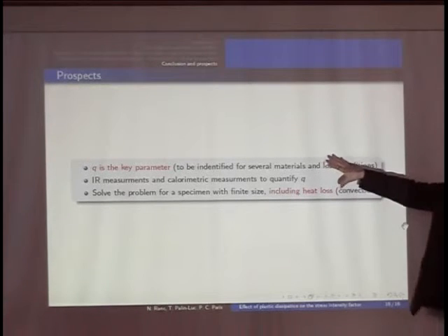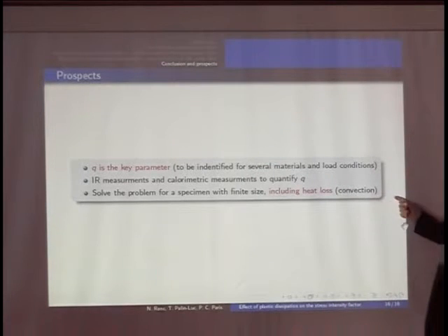Yes. Okay? So in my talk, we are only talking about the monotonic. And this monotonic increasing of the temperature, according to the few experiments we carried out, we tested an aluminium alloy 2024, a C40 steel, and a titanium alloy. This monotonic increasing is very dependent on the material. If you look at the aluminium alloy we tested, the increasing of temperature is very, very small. Yeah, because of conductivity. Yes. If you look at the steel, there is a significant heating. And people who carry out ultrasonic fatigue tests know that for ductile steel, the heating is important. For aluminium alloy, the self-heating is very small.